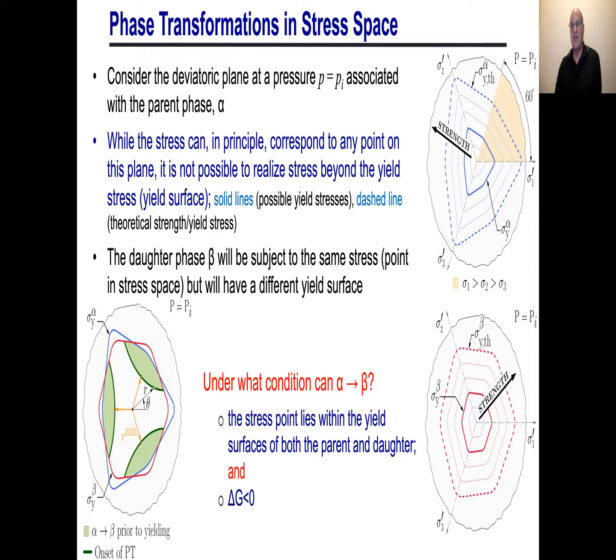And the other condition, which is sort of the more obvious one, is we need the free energy of the phase transition to be negative, a delta G to be negative. So first we need a stress for which the phase transition could happen, that's delta G, and we also have to make sure that that stress is achievable. That is, the stresses lie below whatever the yield strength of the material is. Now, the reason I'm drawing all those different contours here for the stresses is because the yield strength of a given material depends very much on its microstructure. And since it depends on its microstructure, by adjusting the microstructure of the material, I can shift how much shear stress I can apply. It must be less than the yield stress.